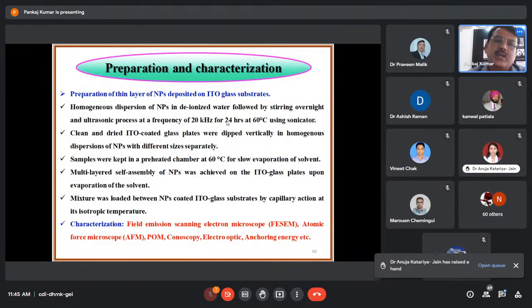Samples were kept in a preheated chamber at 60 degrees C for slow evaporation of the solvent, and a multi-layered self-assembly of nanoparticles was achieved on the ITO glass plates upon evaporation of the solvent. The mixture, meaning the liquid crystal mixture, was loaded between the nanoparticle coated ITO glass substrates by capillary action at its isotropic temperature.